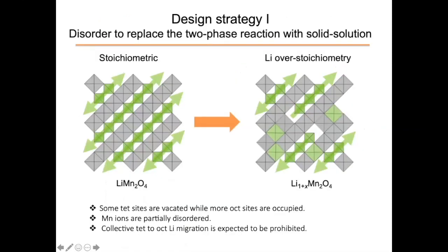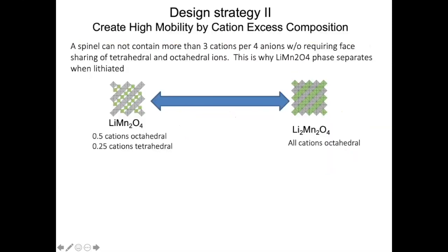And so what is our strategy to get rid of the two-phase region? Well, we decided we're going to partially disorder the spinel. If you partially disorder the spinel, for example, you distribute some of the manganese between 16c and 16d sites. The 16c sites are normally vacant. It's well known from physics that if you create intrinsic disorder, you can kill first order phase transitions. Sometimes they become second order and sometimes they simply go away. And this collective effect of going from LiMn2O4 to Li2Mn2O4 will go away. So that's strategy one for the design.